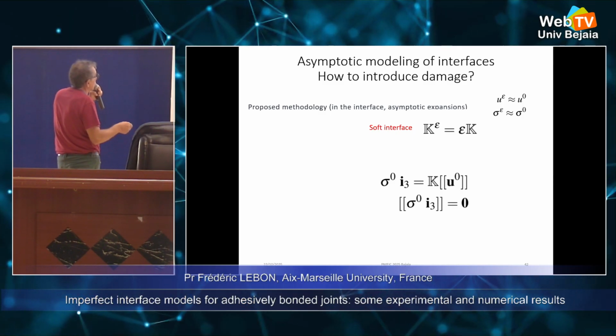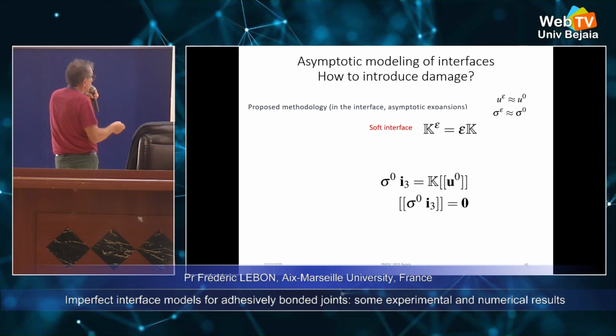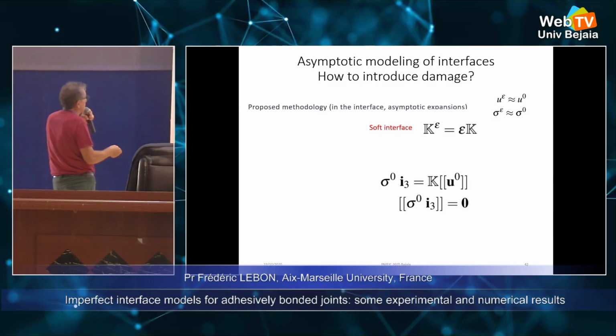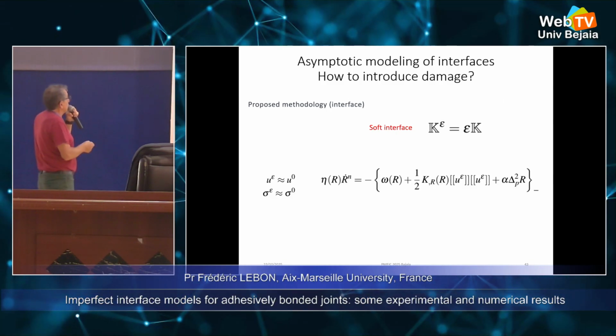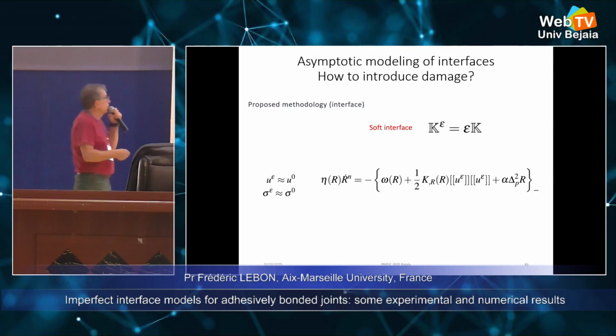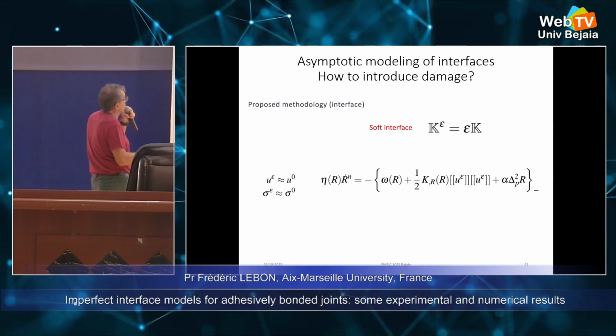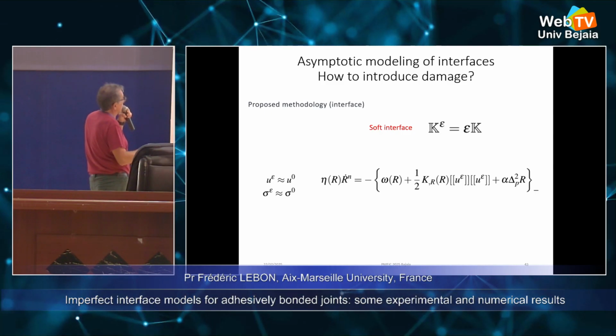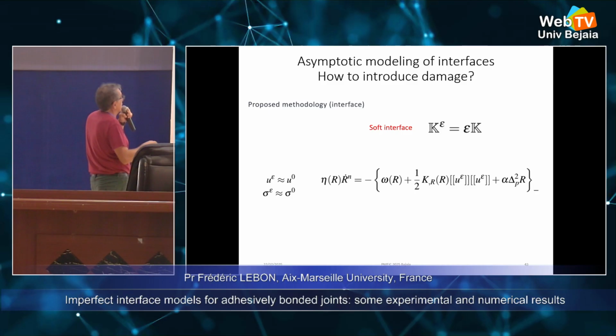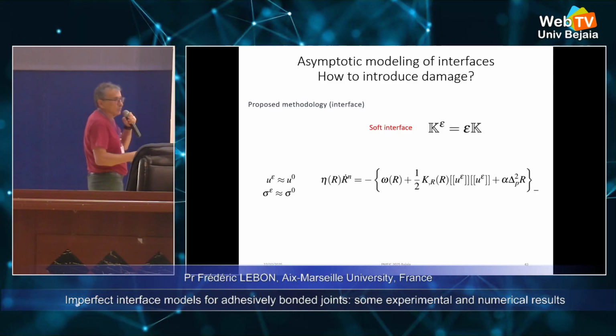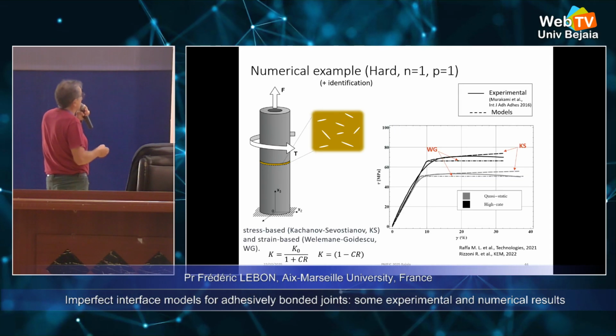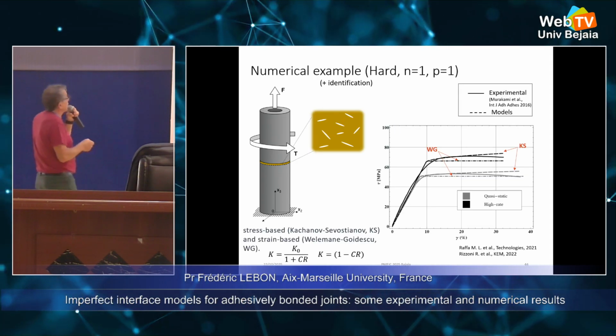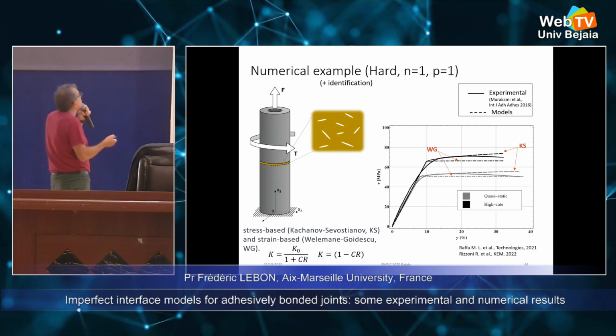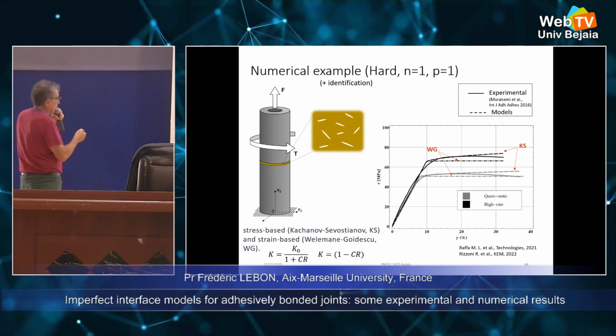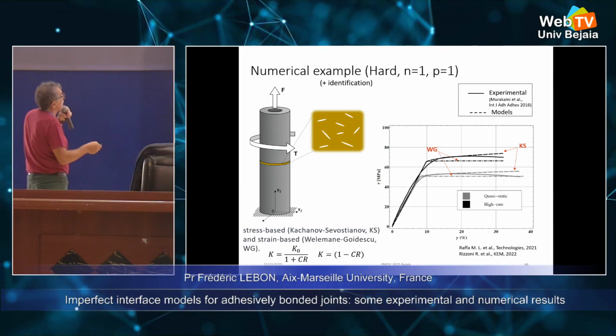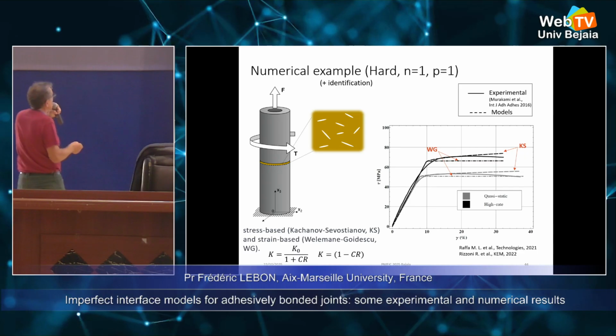So we have this kind of thickness which depends on epsilon. We obtain the classical spring, and after that at order 0 we obtain this kind of law. And in fact, on the interface, here there is an energy of spring. And we have to compare it to the threshold, and so we can proceed to the identification of the parameters, because there are some parameters in the model, and we can compare here with an experiment in the literature due to Murakami. It is a very particular example.